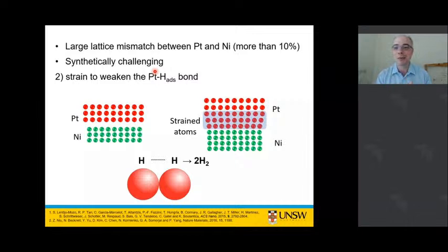So we love this because it's kind of synthetically challenging. Nobody had really ever grown platinum on nickel before for nanoparticles. So we thought that was a great challenge. But also it should make great catalysts because of this mismatch. You should have a lot of strain. So this is our nickel and this is our platinum. And as the platinum's joining on the nickel, it'll be very strained and very compressed together, a lot closer together than it would normally like.